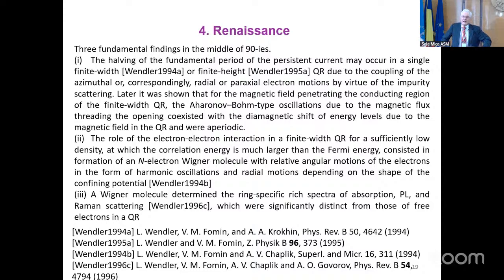Second, the role of the electron-electron interaction in a finite width quantum ring, again with a sufficiently low density, at which the correlation energy is much larger than the Fermi energy, consisted in the formation of an n-electron Wigner molecule with a relative angular motion of the electrons in the form of harmonic oscillations and radial motion depending on the shape of the confining potential.